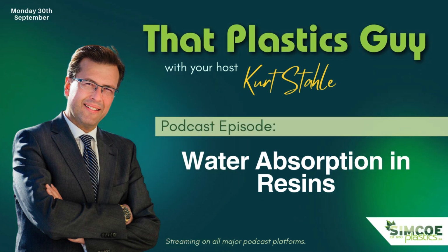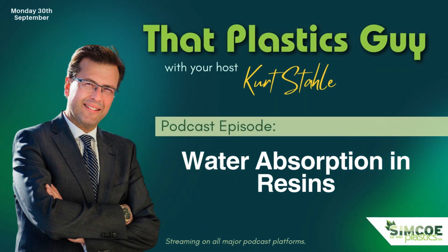Just looking through a couple of other things, 30% glass-filled PET, another common material for maybe under-hood automotive applications. Dry moisture percent, 0.05, maxes out at 0.1%. It's still enough to cause problems. So when you're dealing with hygroscopic materials, I'm repeating myself, dry them, dry them, dry them, and you're setting yourself up for success.